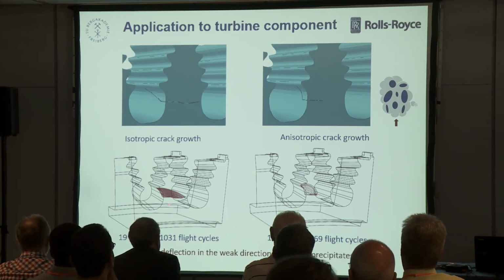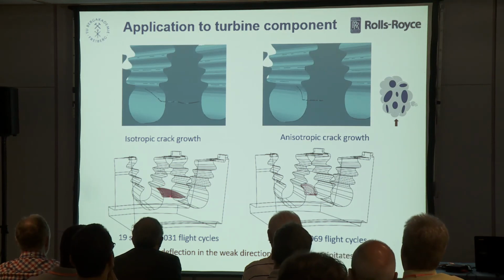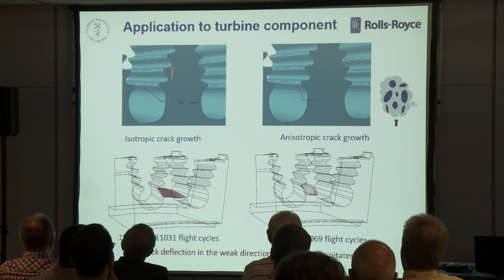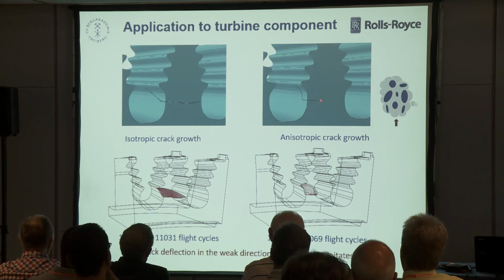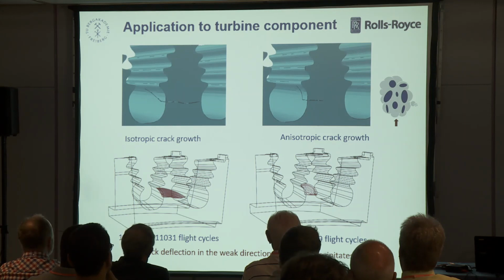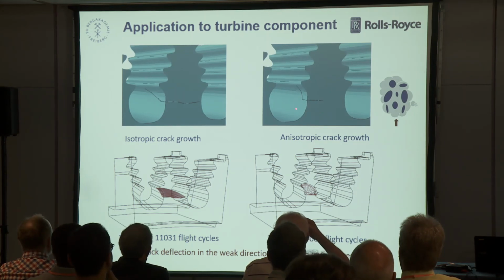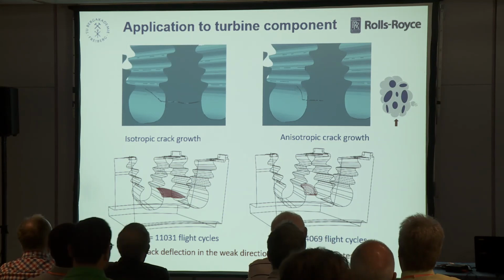And here you see, with isotropic assumption, that the crack fairly follows a direction perpendicular to the maximum load, the centrifugal forces. Whereas for anisotropy, where the platelets are aligned in this direction, the crack will turn its direction more or less parallel. You see it here and here. And we could also simulate 4,000 flights, and the crack attained already this size.